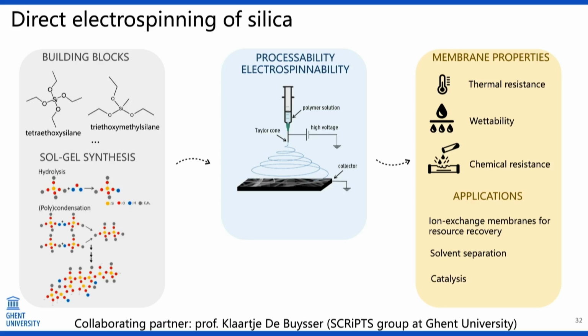This is often done, as you need the organic polymer to make it spinnable. We wanted to spin silica only, so that we didn't have to remove the organic polymer. We could leave out the heat treatment, which also allows us to bring in many more functional groups, which would be removed during such heat treatments. But that makes the building blocks more complex. So we have to start from the precursor building blocks shown here.